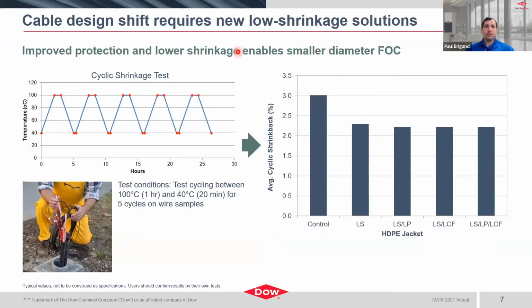So the first thing we'll look at is cable design shifts and the new low shrinkage solution. And what we're looking at here is really the improved protection, as I mentioned, with lower shrinkage than normal or typical HDPE jackets. So what we've done to try and simulate some of the cyclic aging, based on our capabilities within our laboratory, has really been to test, as follows, from 40C to 100C over a period of about a day or so and run several cycles throughout. And so this is one way that we're able to simulate. It doesn't match up exactly to some of the other field tests, but this is what we're able to do to try and simulate.